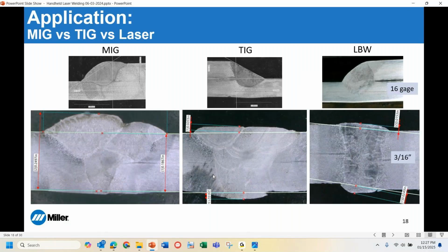So these three diagrams are showing both a lap fillet configuration as well as a butt weld configuration with the different welding processes. The top one being a 16 gauge material, MIG welding. You can see there we get penetration to the root of the weld, and we have quite a large weld bead. TIG welding, because it's such a precise process, we can very intimately control that filler metal to heat delivery ratio and get a more adequately sized weld. And then with the laser welding process, we can easily capture that root and put a nice square plug of penetration into the part without causing a lot of distortion.